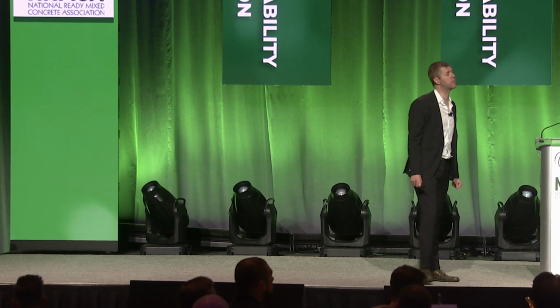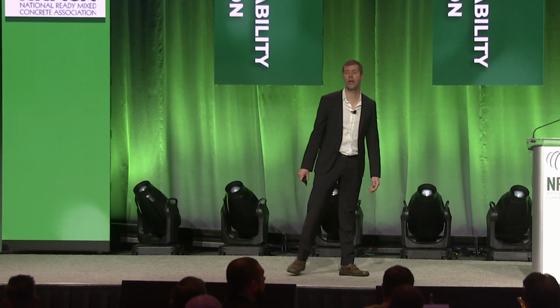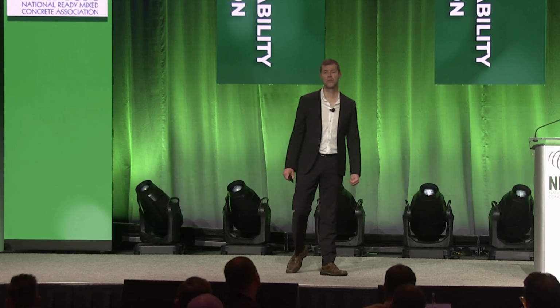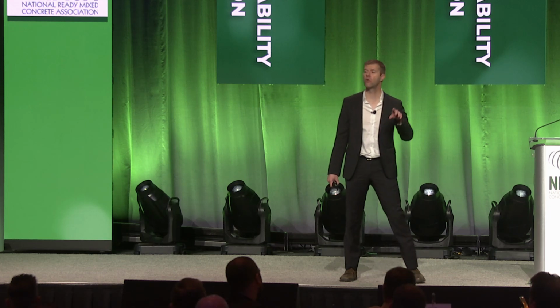Low strengths on job sites are often caused by poor sample handling. And one reason we add a lot of extra cement to our mixtures is to head this off. We put an extra safety factor in our concretes because we don't want this to happen. That's what everyone pays us on. That ain't happening. They're not taking my money away. I'm putting more cement in.